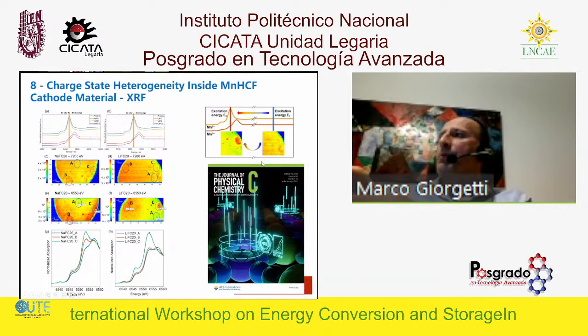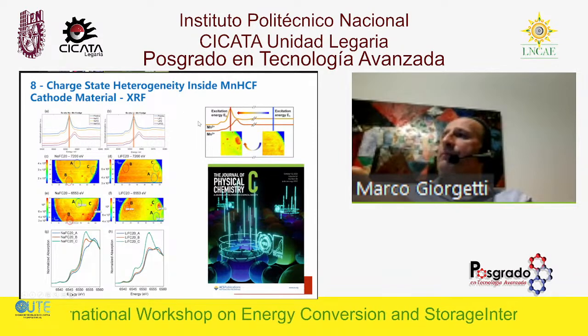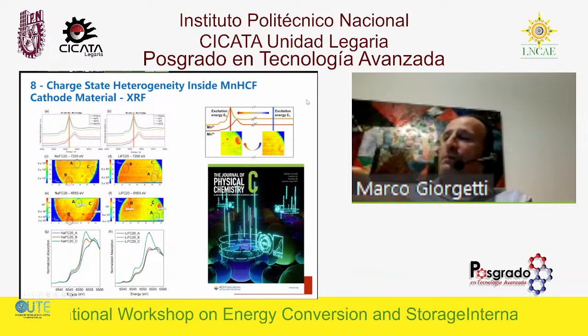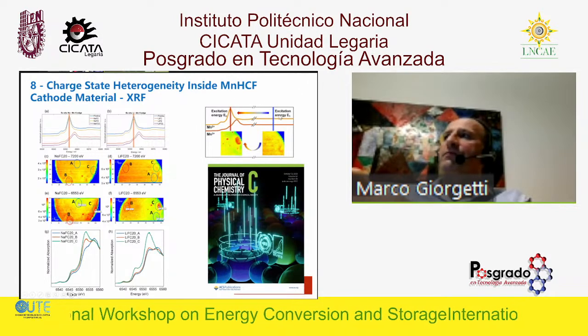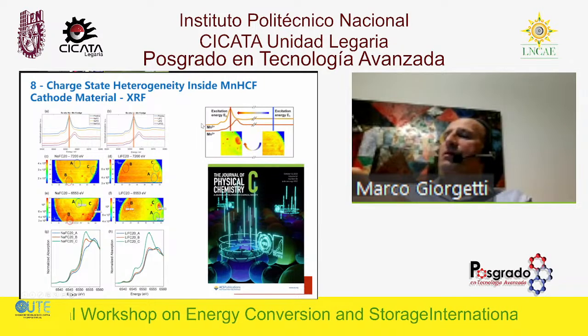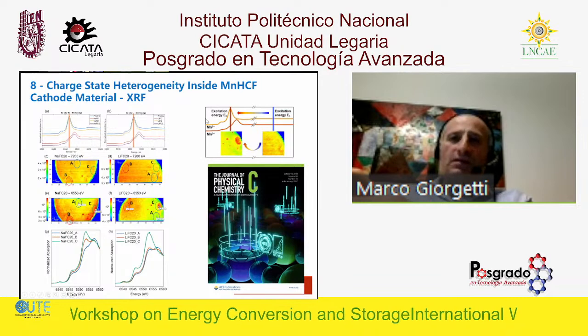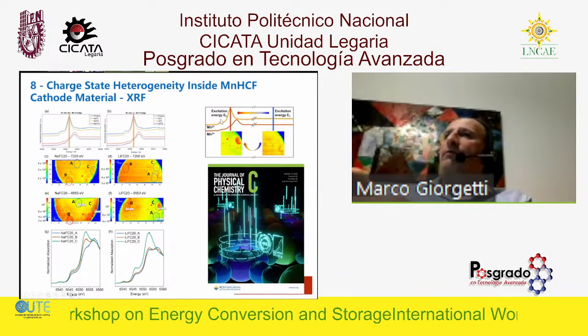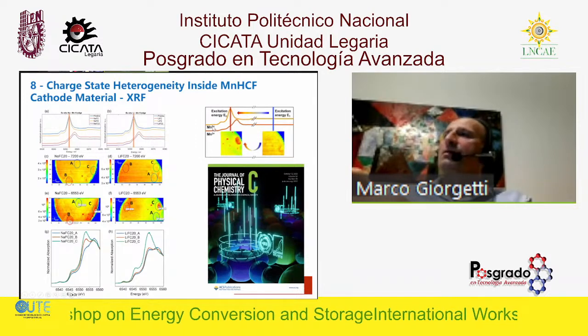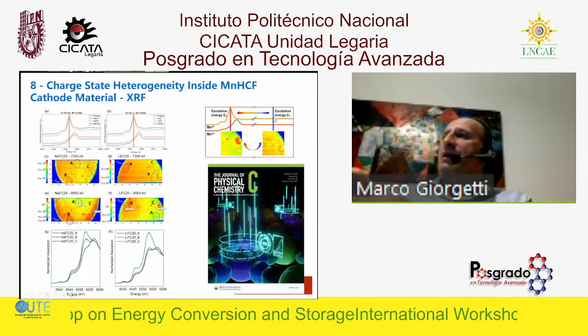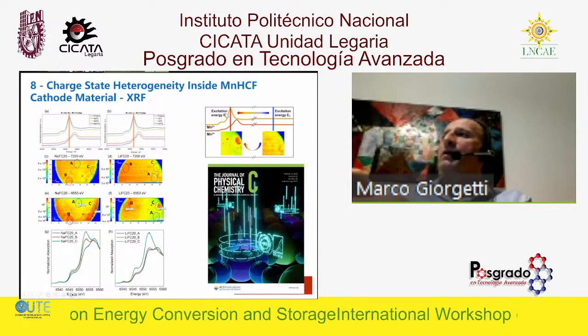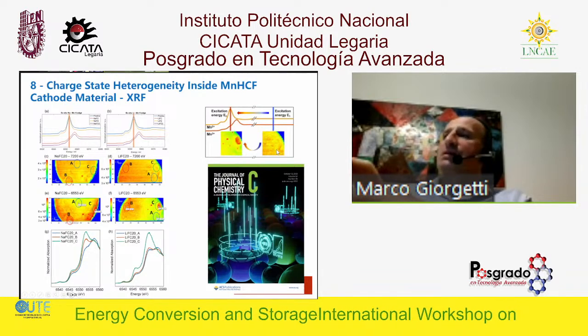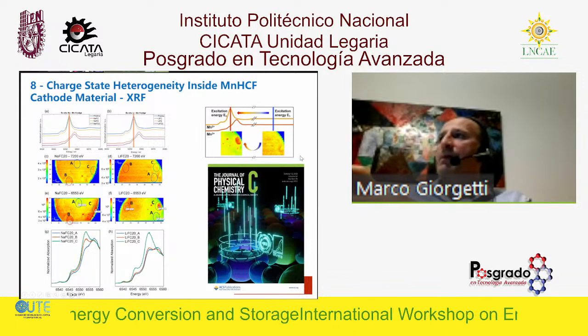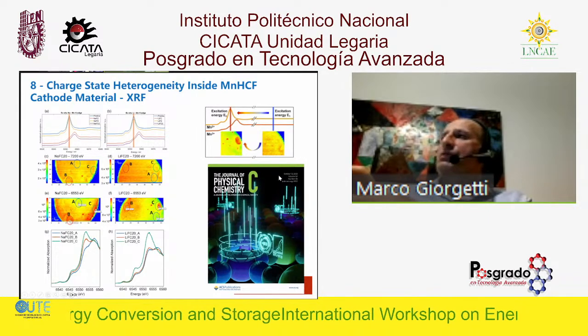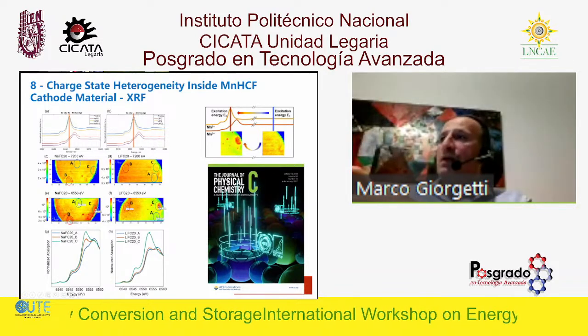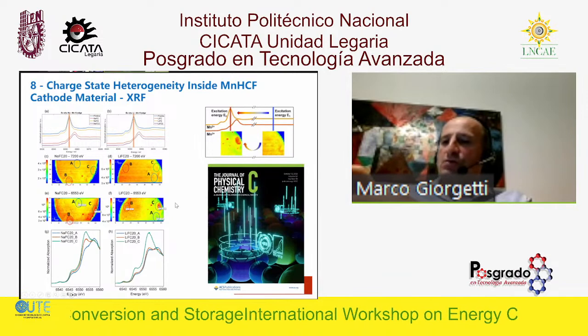And we can see here, okay, let's just see on this. By tuning your edge energy, the energy of the primary beam, in different ways, you can use the sensitivity of the XANES for different oxidation states. And then by tuning this beam energy, here we have two different maps. So basically, we ended up having a charge state heterogeneity inside the manganese hexacyanoferrate cathode material that you can explore by using a beneficial way of use of the synchrotron radiation.